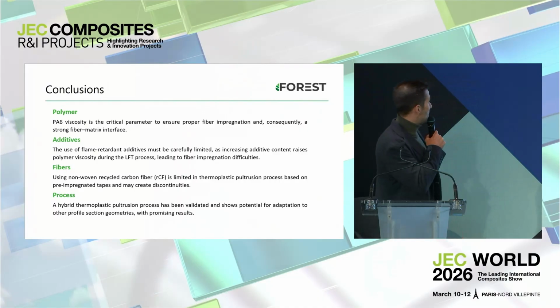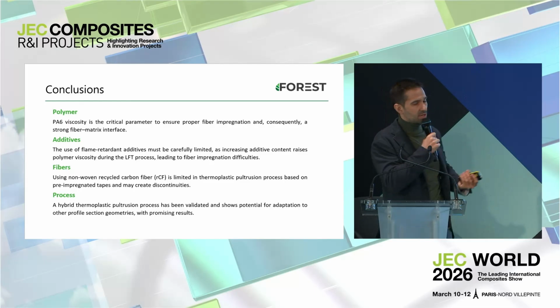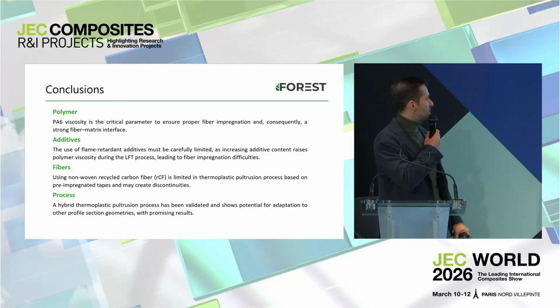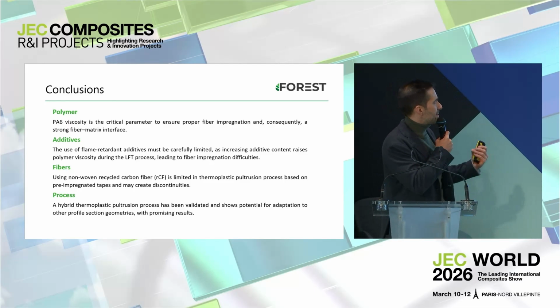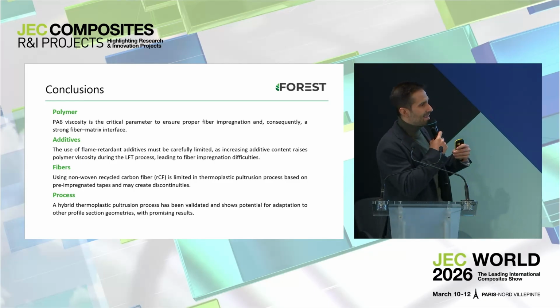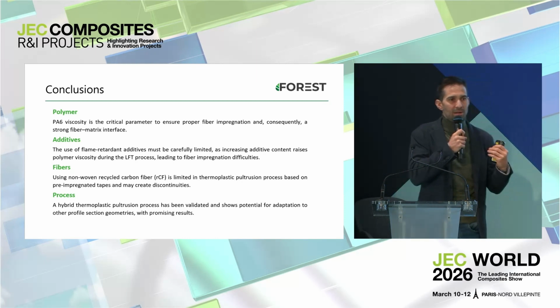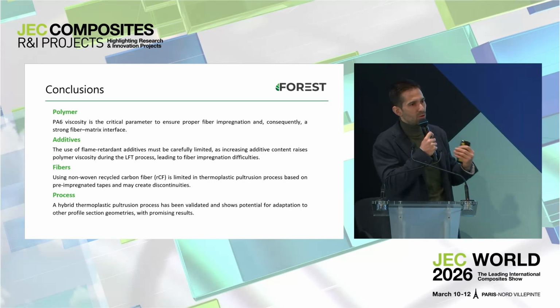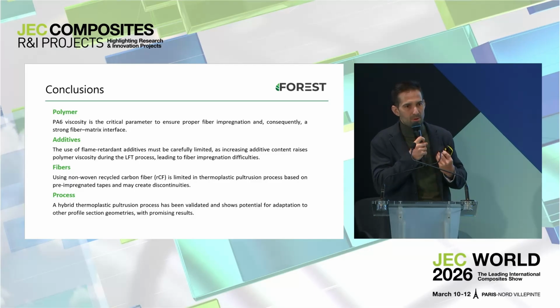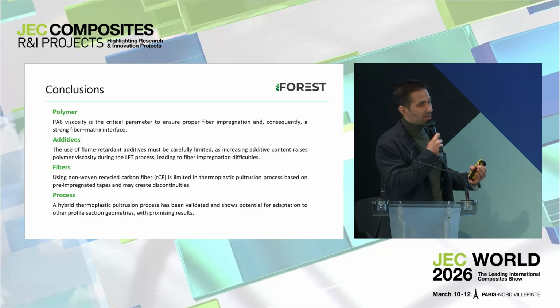And as conclusions regarding the polymer, we know that the polyamide 6 viscosity is a critical parameter for this process. To ensure proper fiber impregnation and a strong fiber-matrix interface, the thermoplastic has to be very liquid, not very viscous, because otherwise with this method we cannot impregnate the fibers properly. So this is a critical parameter. Thankfully, BASF has developed low viscosity polyamides, polyamide 6, which is quite tricky.